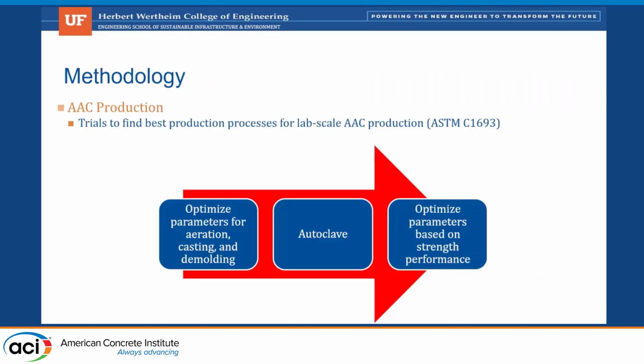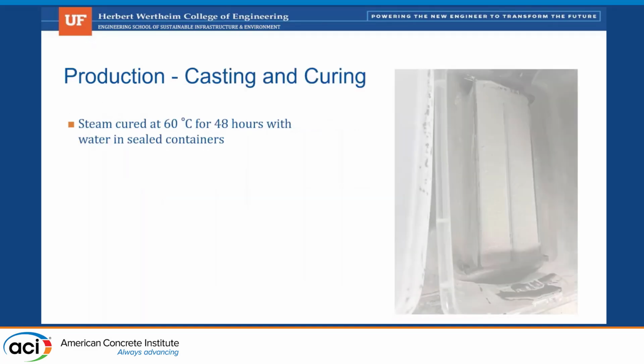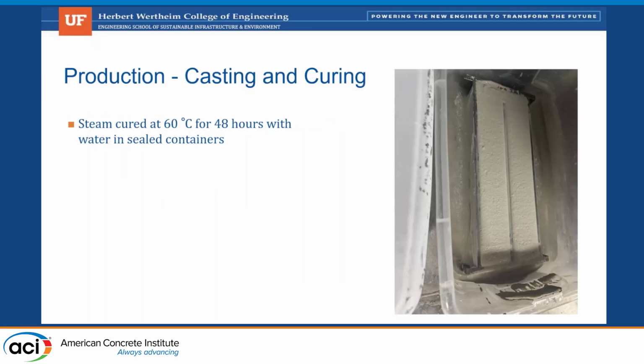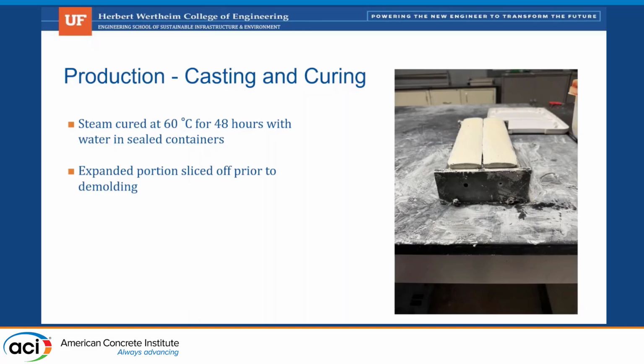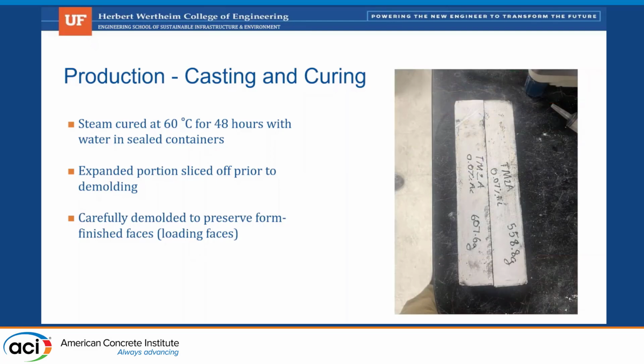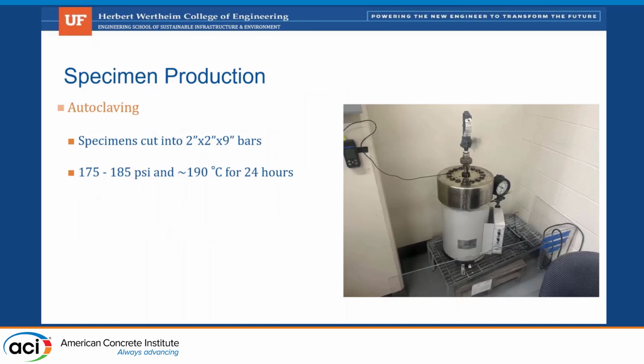Okay, so we did our trials to find the best production processes for AAC production, and I'm going to go over these very briefly. Basically, we steam cure for 48 hours in water-sealed containers. Then we slice that portion off. You can already see there is some expansion in the molds, and this is the exact same process they have at the Aircon facility. We just do it in the lab, much smaller. Once they're demolded, we preserve their form-finished faces, the loading faces. That's our specimen production.